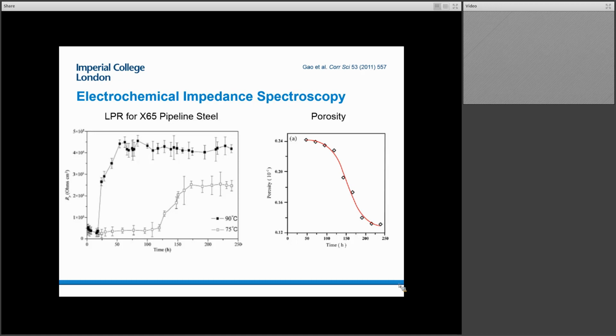And so they've gone now outside of those bounds and looked at the porosity. One of the things that you can look at is actually seeing the porosity and how it's evolving. And so they're able to further substantiate what they're seeing in the electrochemical data. So we understand now about how the resistance to charge transfer is changing. We understand all of these details, but we can actually see the porosity evolving from complementary experiments. And so together, this is all forming a really nice story that's quite helpful. But impedance alone wouldn't provide all of this data.